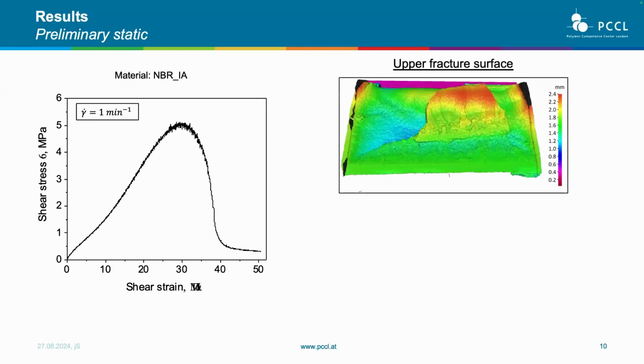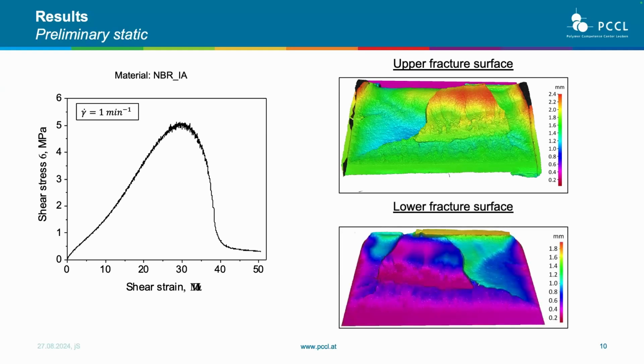However, what about the fracture surface? This is a color map of the fracture surface with the height, so the thickness of the adhesive part, the rubber part. These are the upper face and the lower surface, and they are specular, of course. But what I want to draw your attention to is that in both cases, in the very lower part, we have a really thin remaining layer, while getting to the upper part, we have a thicker and thicker remaining part of the thickness. And of course, this is specular until more or less here, where we have the counterpart of the thickness.